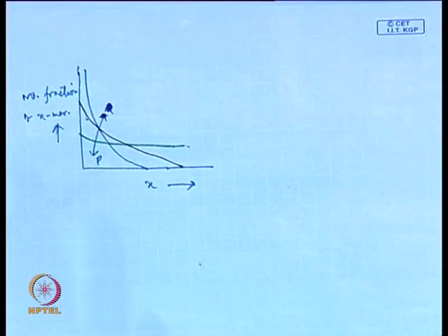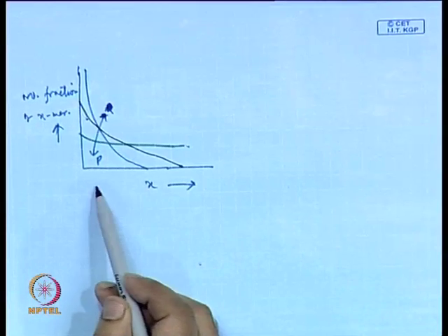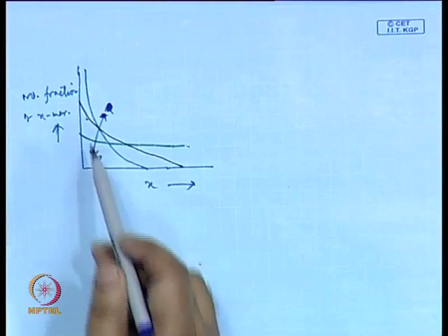So, what does it mean that in case of step polymerization, at any point of time, whether it is a small conversion or high conversion, the molecules present in maximum number are the monomers, because monomers have the least number of structural units. If you look at the distribution, the maximum is on the left-hand side, which is the minimum of x, that means these are the monomers.